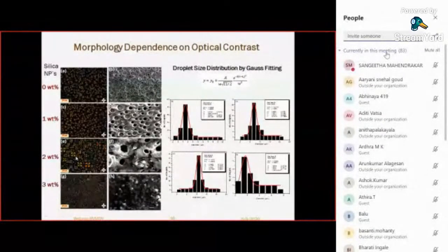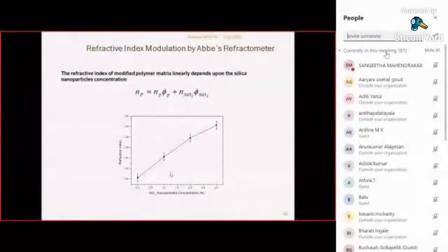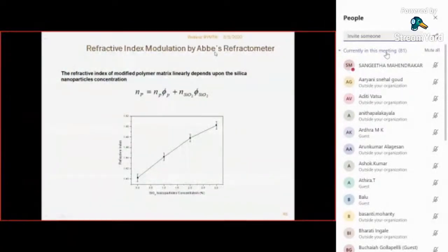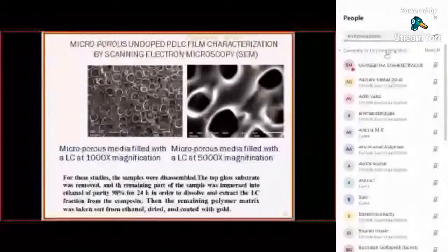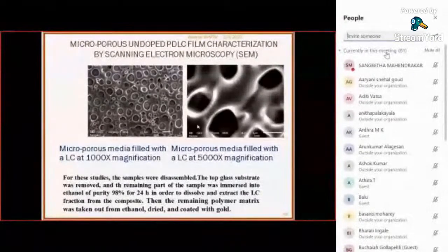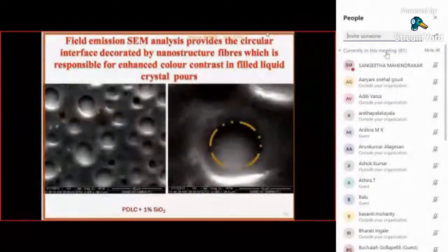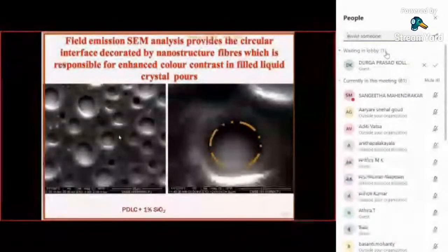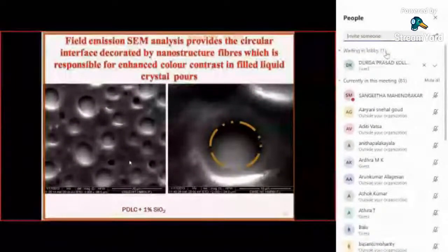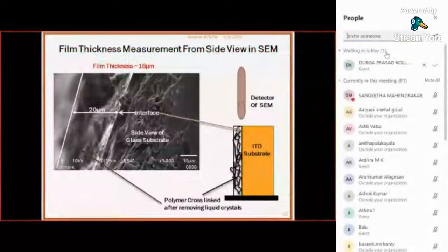So this is again the contrast, and this is the important parameter which has been studied, the refractive index. Refractive index also changes with the doping of nanoparticles, which was investigated with the help of an Abbe refractometer. And again the pore size: here I have shown lower magnification 1000x, and here 5000x. This is the pore size taken from scanning electron microscopy, and this is the micrograph of nano-doped liquid crystal. We are getting a near symmetrical structure at the micron level. In the case of 1 weight percent silica nanoparticle, we get better contrast, and we have even measured the thickness of these materials.